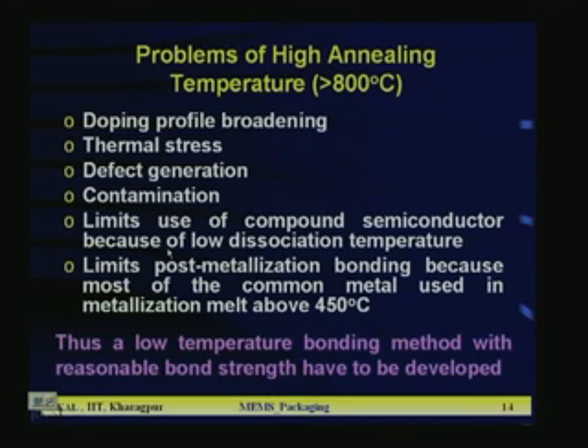And the last 2 points are again very crucial. What are those? It limits the use of compound semiconductors, because compound semiconductors are basically a combination of different elements, for example gallium arsenide, indium phosphide. But at high temperature the composition will not be maintained, because gallium and arsenic have different evaporation points. So, at high temperature the stoichiometric ratio of those compound semiconductor elements will not be maintained, they will change because of different melting points or different evaporation points of different elements in the compound mixture. So, that is one problem.